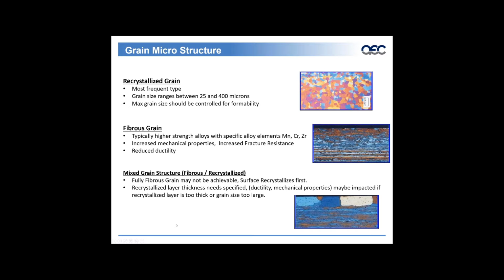Recrystallized layer thickness needs to be specified. Ductility and mechanical properties may be impacted if the recrystallized layer is too thick or the grain size is too large. So we're monitoring the grain size of the recrystallized layer as well as the band thickness of that layer itself. To go further in the webinar, we're going to talk more about the mixed grain structure, the fibrous recrystallized.